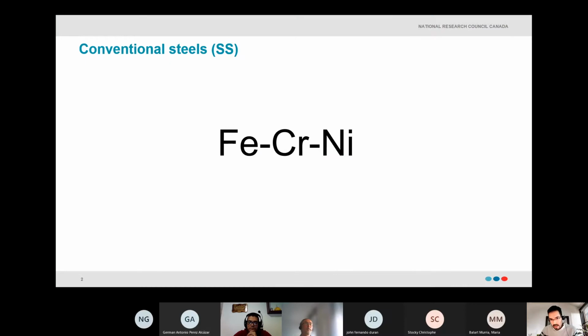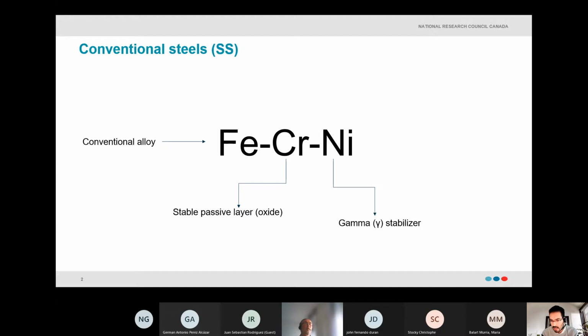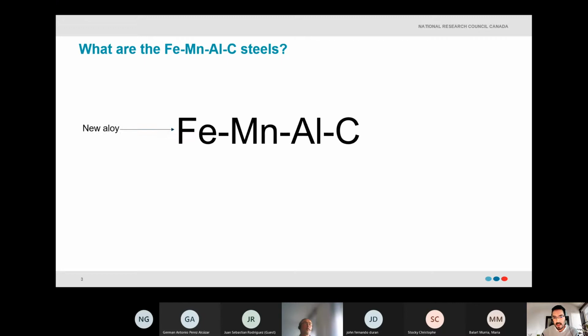Conventional steels are many, but I decided to put here the stainless steels. We already know that chromium forms a stable passive layer, and nickel is a gamma stabilizer. Both of them are expensive elements. So what are the iron, manganese, aluminum, carbon steels? Basically, it's a kind of new alloy which consists of manganese, aluminum, and carbon. Manganese has the same effect as nickel, because manganese is a gamma stabilizer and a solid solution strengthener in the substitutional way.